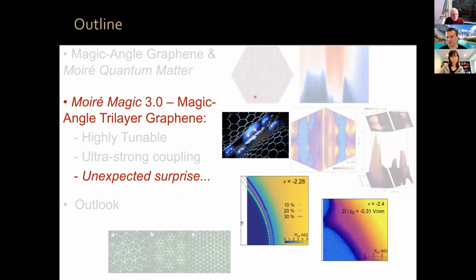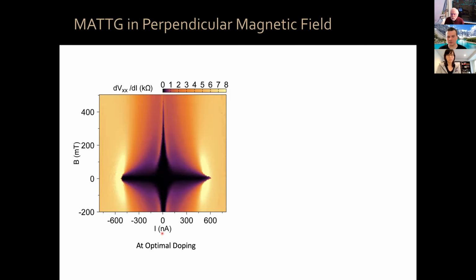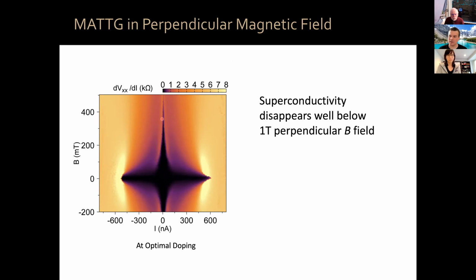Now, let me tell you in the last 10 minutes or so about an unexpected surprise that we found out when we started to do in-plane magnetic field measurements. Now, as I showed earlier, in a perpendicular magnetic field, if you are at optimal doping, superconductivity disappears well below 1 Tesla. This is due to the formation of vortices, the standard orbital effect in superconductors.